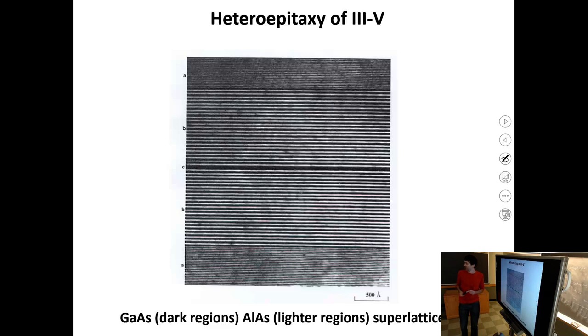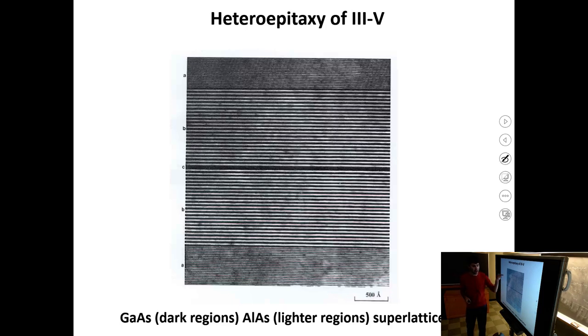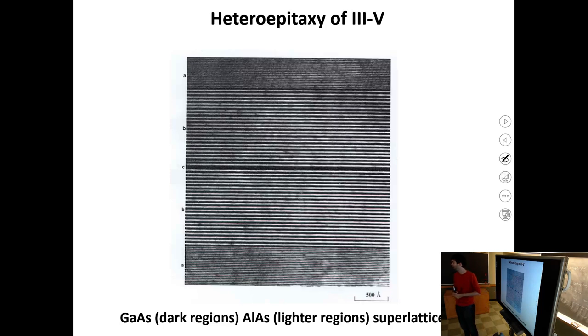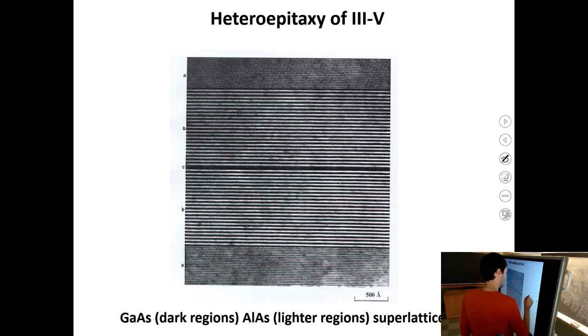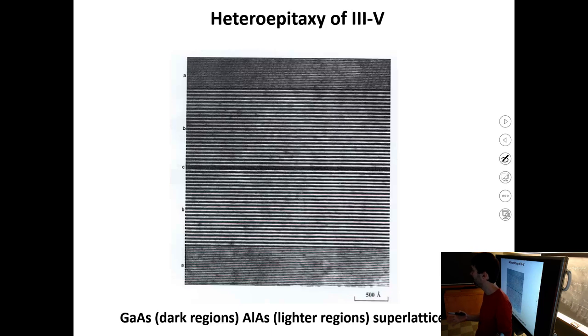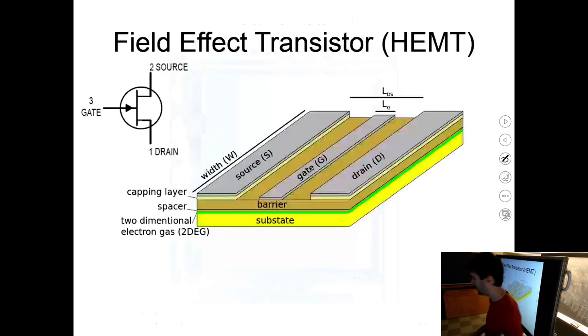This TEM image shows a heterostructure between gallium arsenide and aluminum arsenide. One semiconductor gives slightly higher contrast than the other. This is not a high-resolution picture so you don't see individual atoms, but you can see the different layers stacking up. This is what MBE can produce — for example, a structure of this complexity to generate a quantum cascade laser. These materials are not naturally occurring; we are creating new materials unavailable before — that's the power of hetero junctions.